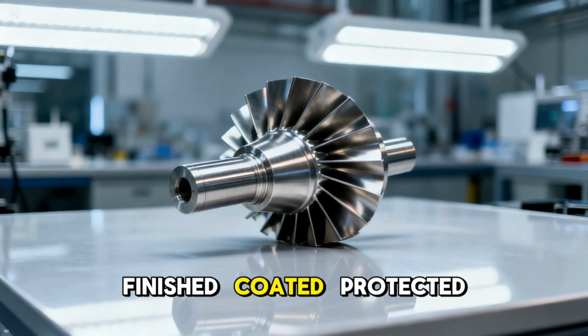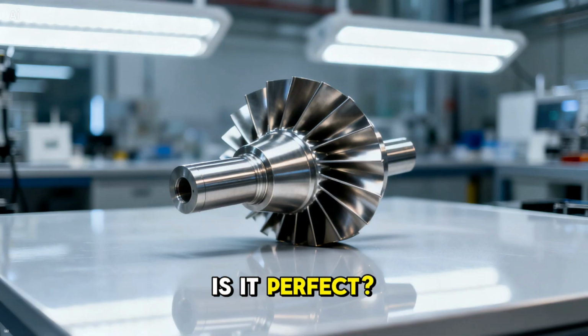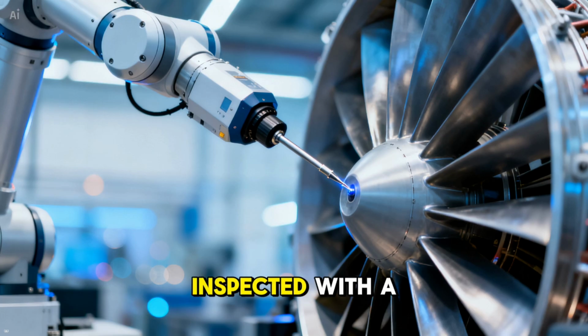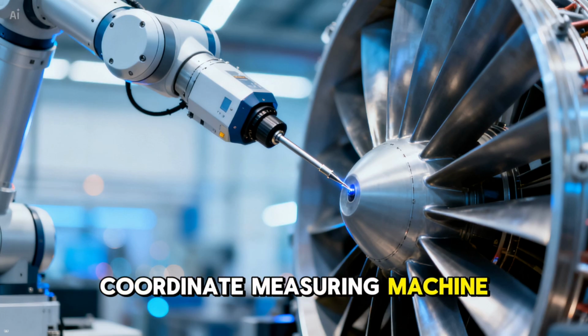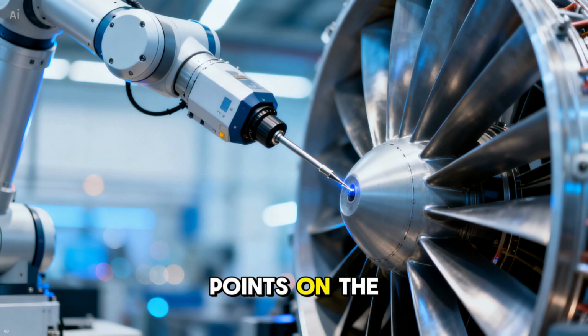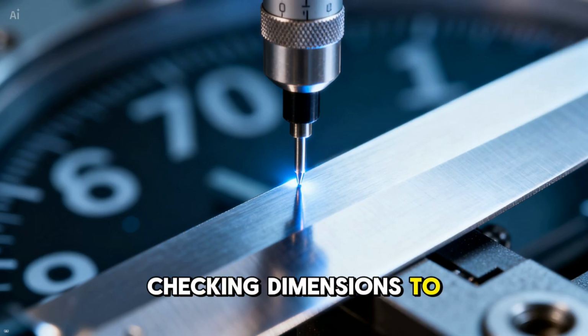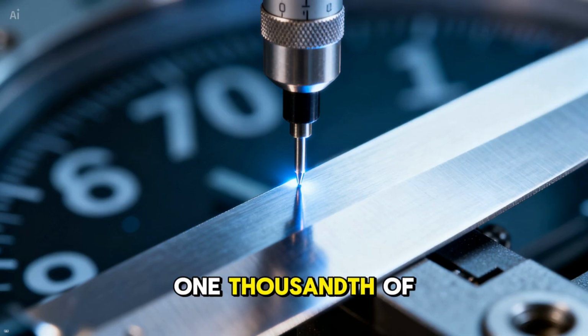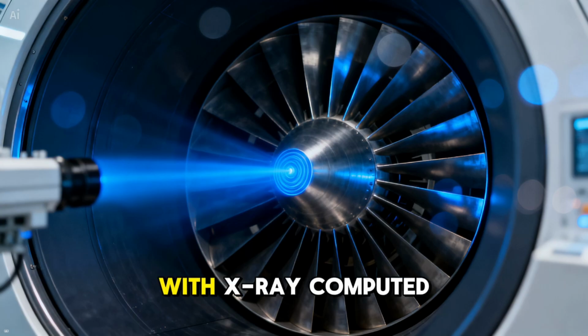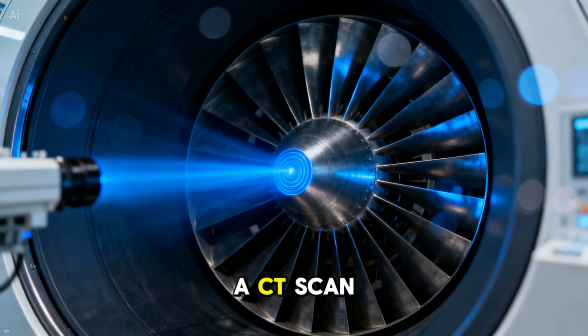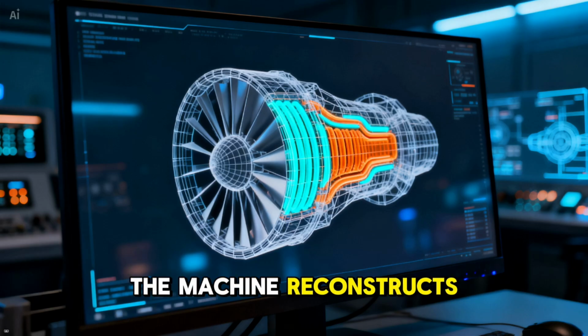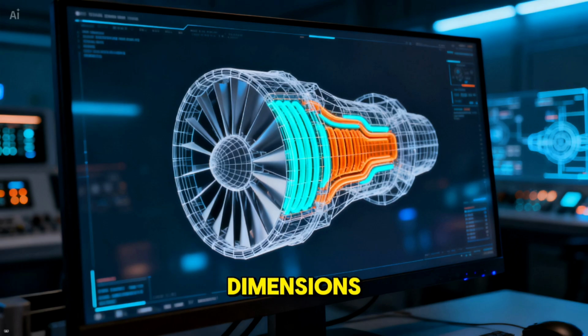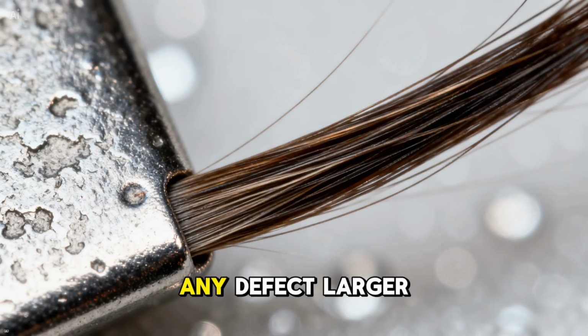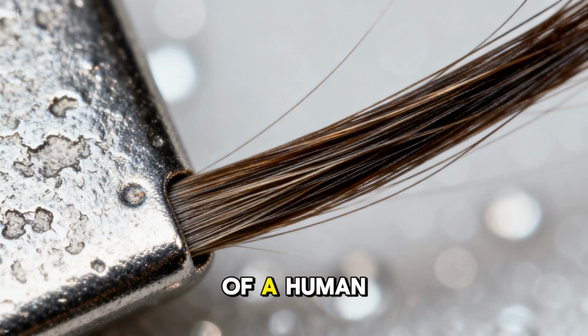The blade is finished, coated, protected. But is it perfect? Time to find out. Each blade is inspected with a coordinate measuring machine. A probe touches 5,000 points on the surface, checking dimensions to within 1 micron. 1,000th of a millimeter. The blade is scanned with X-ray computed tomography, a CT scan for metal. The machine reconstructs the internal structure in 3 dimensions. It checks for voids, cracks, and wall thickness variations. Any defect larger than 50 microns is rejected. 50 microns? Half the width of a human hair.